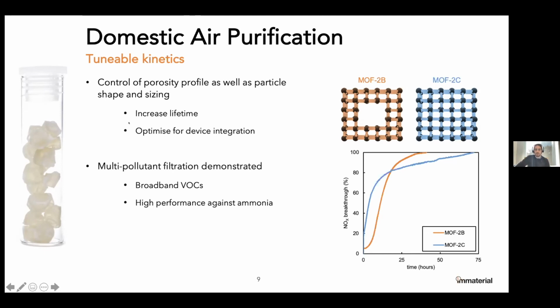Alongside the focus on NOx, we have had a look at how they behave with other pollutants as well. For this MOF2, which is our product code for it, we looked at broadband VOC absorption at realistic parts per billion type concentrations, and we see quite a similar performance to what you would see with an activated carbon. The activated carbon does slightly better on some species, and the MOF does slightly better on others, but overall you're absorbing a similar amount. But possibly of more interest is that this same structure, as well as having good performance with NOx, has very high performance against ammonia. So the multi-pollutant aspect of these materials is something else that we're interested to understand in more detail and could be very valuable in applications as well.